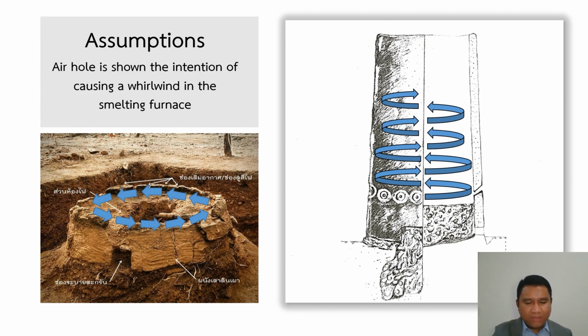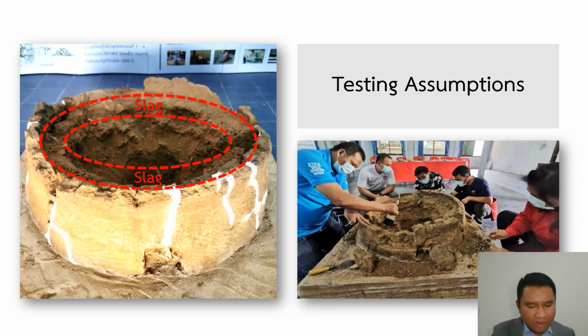The archaeologists assume this boring hole shows the intention of causing a whirlwind in the smelting furnace. To verify the assumption, the archaeologist team studied the internal structure of the furnace until we discovered that inside the furnace, slag was found along the edge of the furnace wall, shaped like a circle. Why did we find nothing in the middle area of the slag? So we assume that the blowing holes are likely to generate high heat only around the inner edge of the smelting furnace, and the high heat may not reach the center of the smelting furnace.